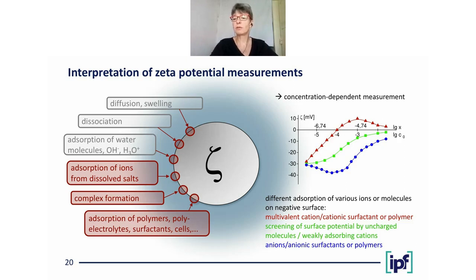And if we have uncharged surfactants, for instance, or other weakly adsorbing species, we see a screening of the Zeta potential, a decrease of the absolute amount of the Zeta potential.